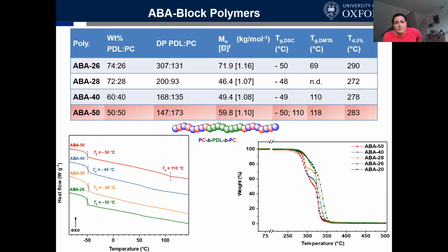And we have been able to vary that so that we hit compositions, for example, where we have about 25% of the blue-red block, and that would be typical of a thermoplastic elastomer. So that we would call a hard block, and for a classic thermoplastic elastomer we have somewhere between 20 and 30 weight percent, usually, empirically. We've also been able to hit compositions where we have a 50-50 mixture of them, and that's the one I'm going to talk to you about today.